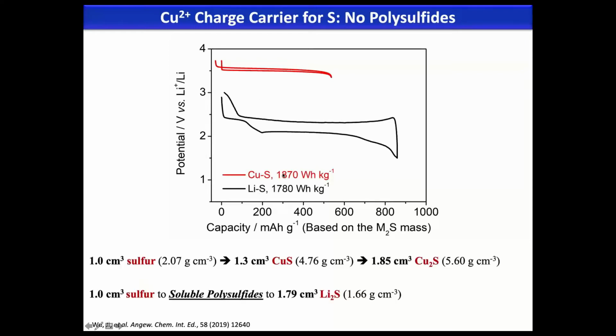So for the sulfur system, it's very interesting. Another point here is, because of the strong binding of cuprous copper and cupric copper with sulfur, there is no solubility of polysulfide whatsoever. It's all a solid conversion. But for the lithium case, you're going to have this metamorphosis of different phases, and some of the phases in between are simply out of control. The polysulfide moves everywhere, creating a layer of plating, a mass of insulating lithium sulfide, right? Now, if you look at just the solid phase, the cupric sulfide and the cuprous sulfide are almost conductors, better than semiconductors. So they can behave much better if you just shrink their particle size to submicron. But for lithium sulfide, you have to make it really nano-sized, right? Probably less than 5 nanometers.